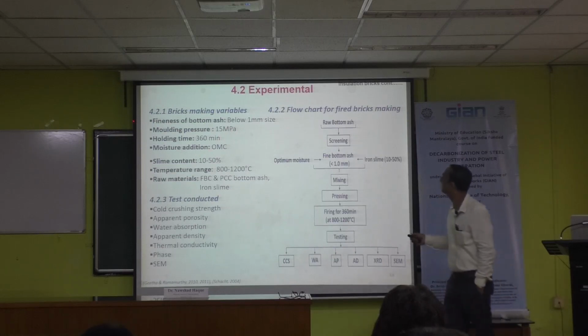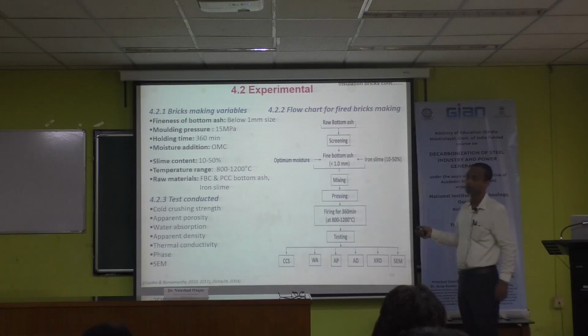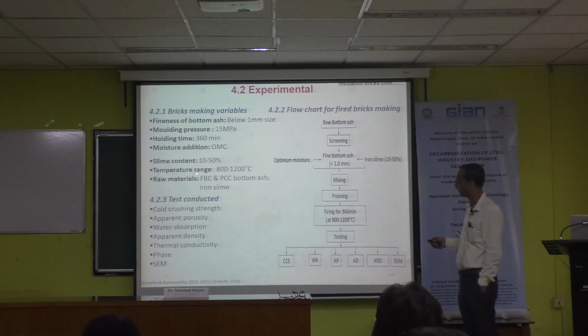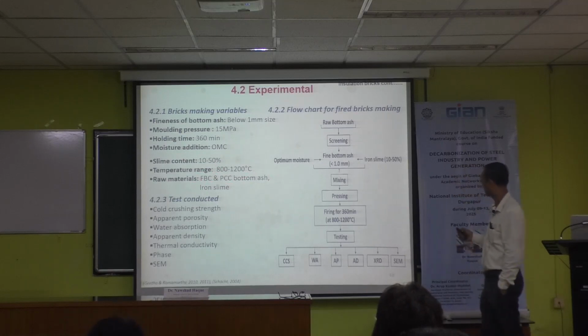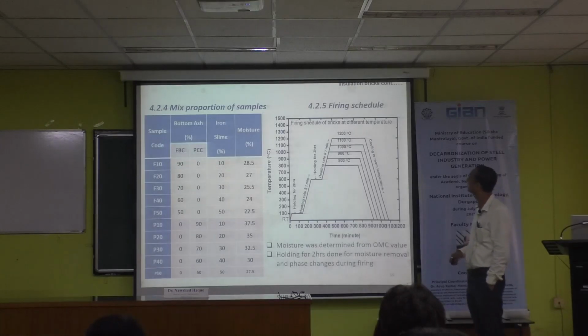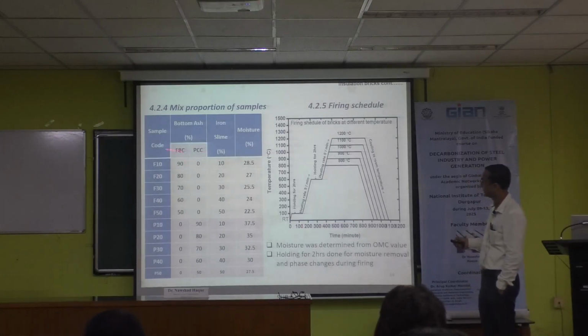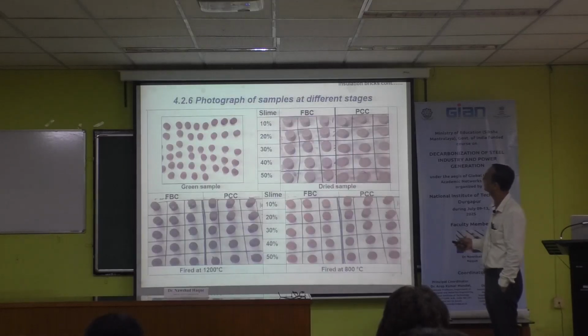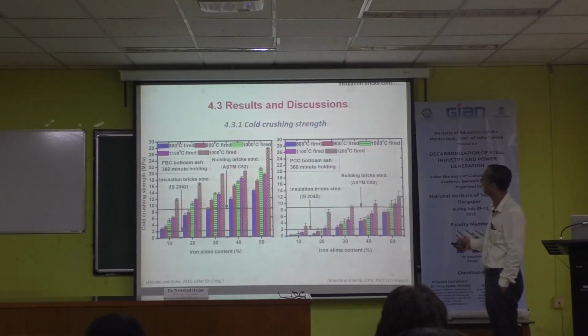We prepared it with the fineness of the bottom ash at only 1 mm, whereas in case of geopolymer it was 0.001. The slime content will vary up to 50%, and different temperatures are required. We tried for FBC and PCC products, both. This is the screening of the slime content, mixing, testing, firing, and these are the different heating cycles. We have taken FBC and PCC in different compositions and fired at different temperatures, and these are the results.